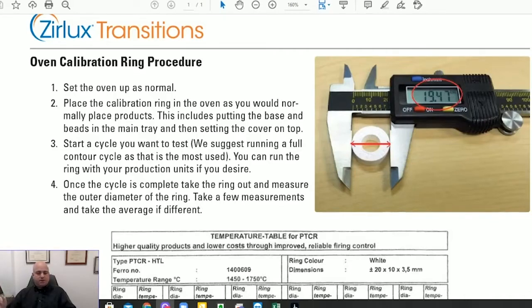Now, I want to emphasize that just because you set your parameters at a certain temperature and the digital reading says that temperature of, let's just say, 1480, it doesn't necessarily mean, without testing it, that that's exactly what's happening within the sintering oven. It's critically important to make sure that the temperature occurring within your sintering oven is the right one. So by placing this ring into your sintering tray and sending it up with your restoration, once it sinters and comes down and cools, you can then take it over to a digital caliper, as you see here, and measure the diameter of this.